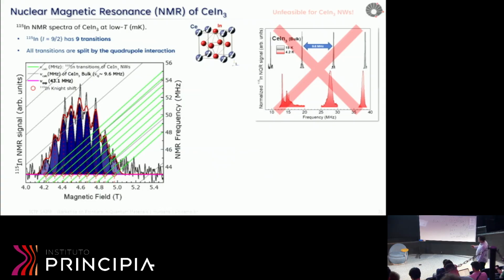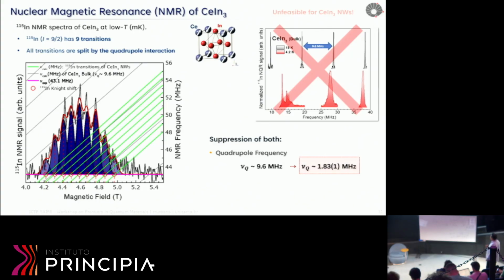So the green lines here now match what our spectrum displays for each position line. These are the new frequencies, but we had to consider different parameters in these calculations, which I'm going to explain later. But the first important result here is that nu Q changed from almost 10 down to 1.8. This is a drastic suppression of the crystal field, which was actually suggested by the analysis of the entropy from the specific heat. Now we could prove that, actually shrinking our spectrum here.